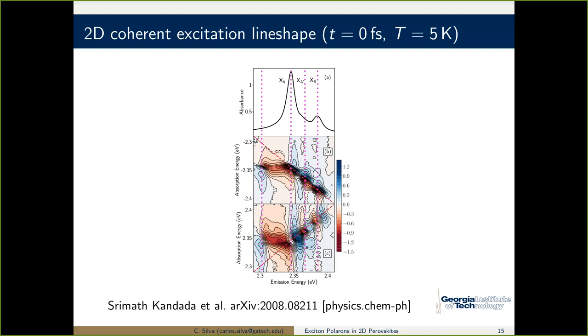I'm not going to prove to you, but I am just going to tell you that if we go and look, I've shown you basically the absolute amplitude of the spectrum. But this being a Fourier transform technique, I can also show you the real and imaginary contributions to the two-dimensional spectrum. For a simple transition, the real part should look like an absorptive spectrum. For the people who remember our electrodynamics course, it's backwards from what we would have told you there, but the real part of this two-dimensional spectrum is an absorptive spectrum.